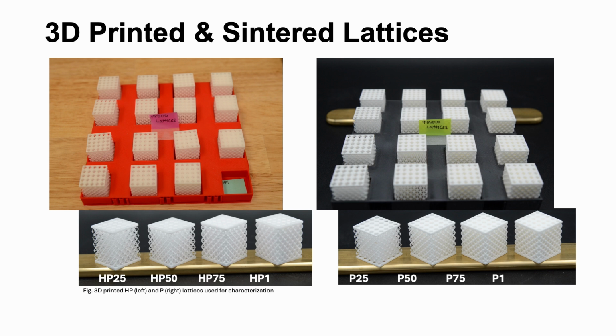We made these sample holders to keep track of all of the lattice types. The ones in the red sample holder would be the 99% alumina, and the ones in the gray holder are 94% alumina. We also took images of all the lattices side by side, as seen here in the bottom. The lattices labeled HP refer to the 99% high purity alumina, and the 25, 50, 75, and 1 refer to the strut diameter. The lattices labeled P refer to the 94% alumina lattice structures.